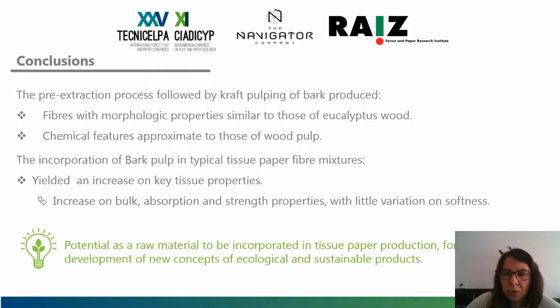and eucalyptus pulp. Also, we found that the incorporation of bark pulp in typical tissue paper furnish mixtures resulted in an enhancement of key tissue paper properties such as bulk, absorption, and strength properties with no significant variations of softness. Thus, in light of this, we see that bark pulp could be a potential raw material to be incorporated in the production of tissue papers for the development of a new concept of products more ecological and sustainable.